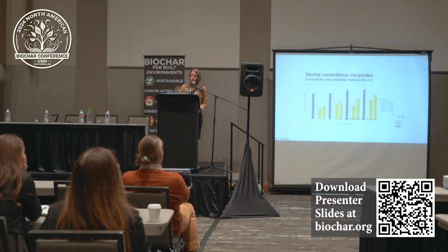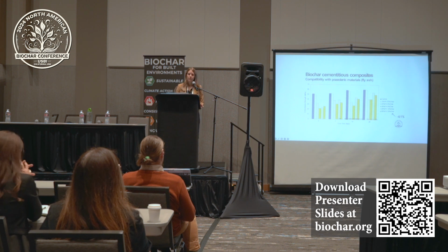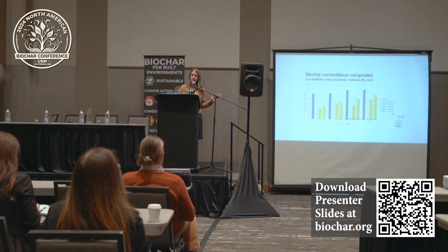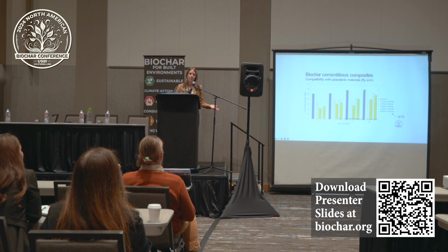What we find is that when we combine this solution with the biochar solution, so now we've got 30 to 40% of our cement replaced with some combination of the fly ash and biochar, we see increased strength gains compared to the fly ash solution alone. Now, we would anticipate also that this would continue to strengthen up to 56 days, just like most pozzolanic materials. And so this is, again, great news because we can now use some of the solutions that we've already been using, but accelerate the strength gains.